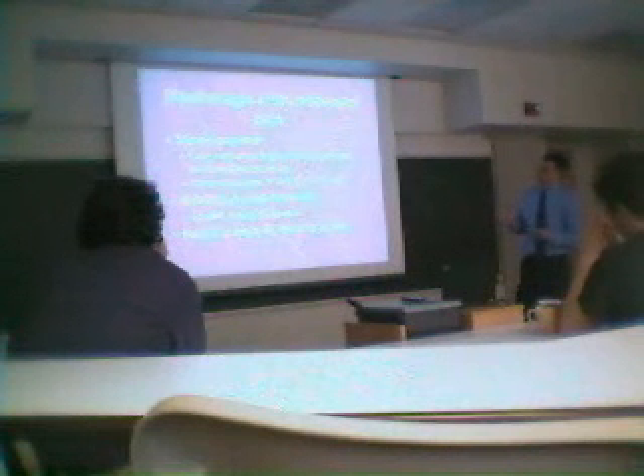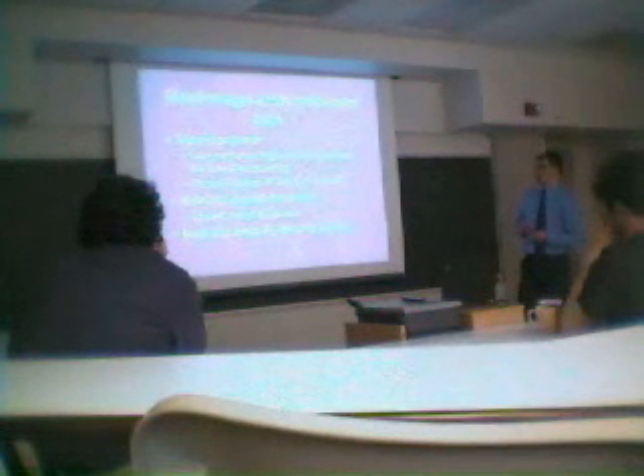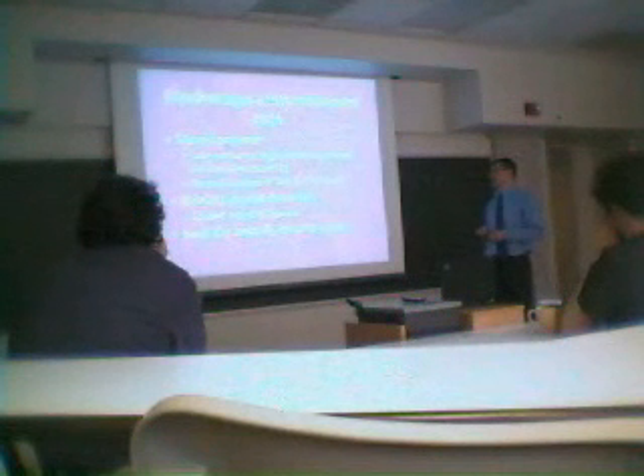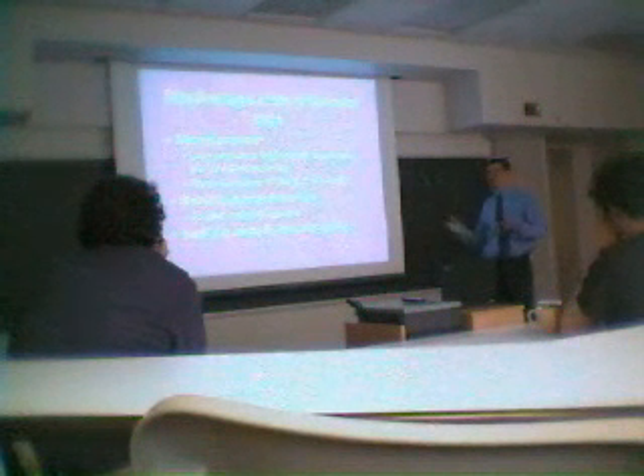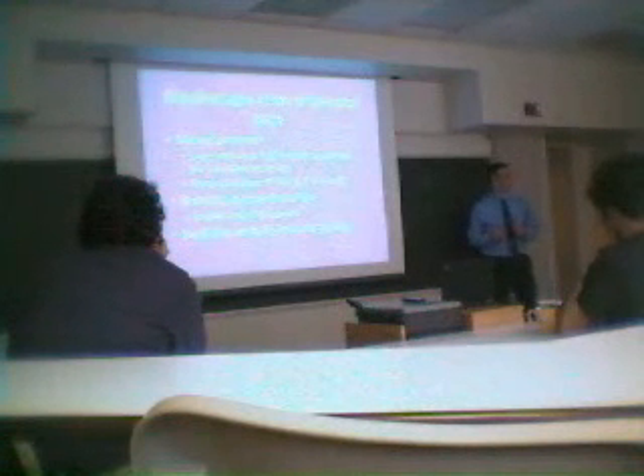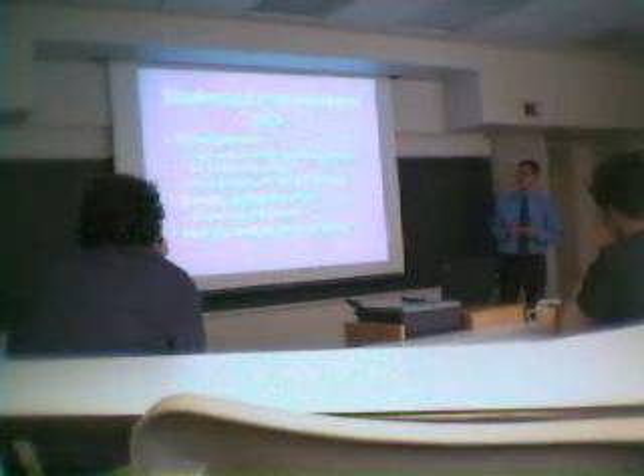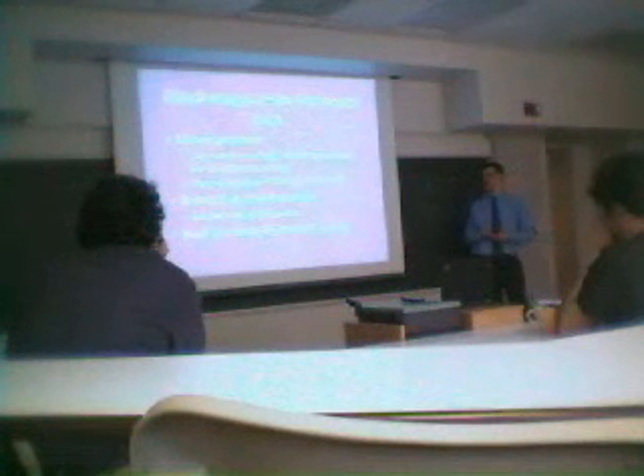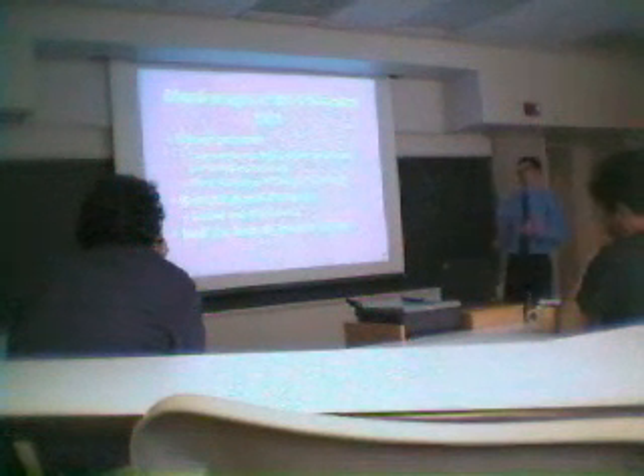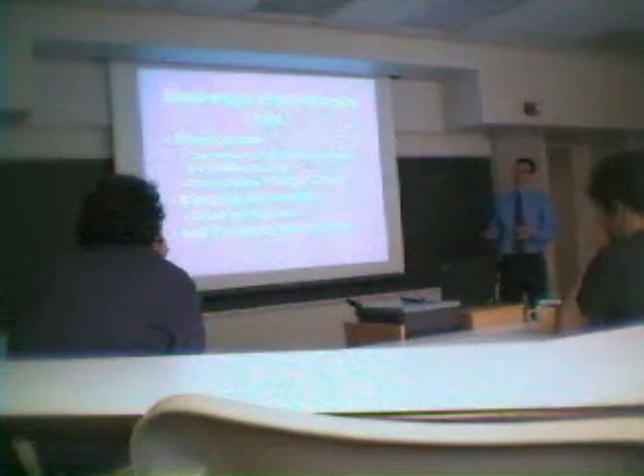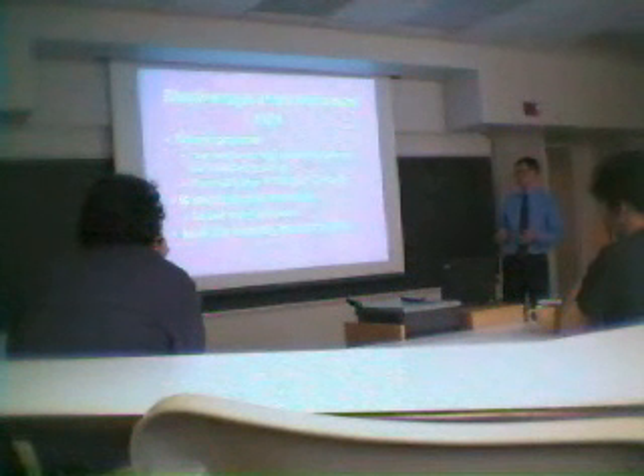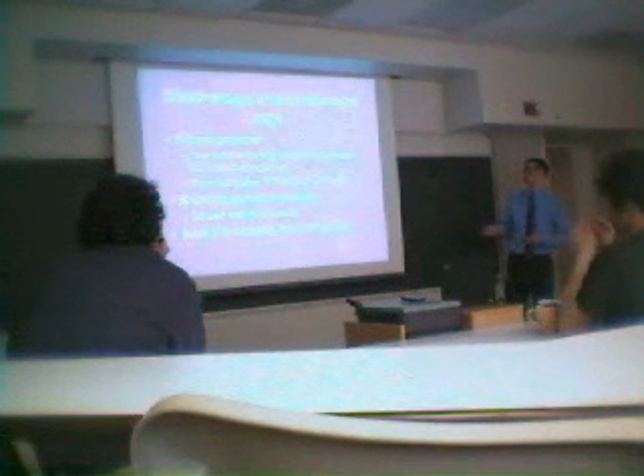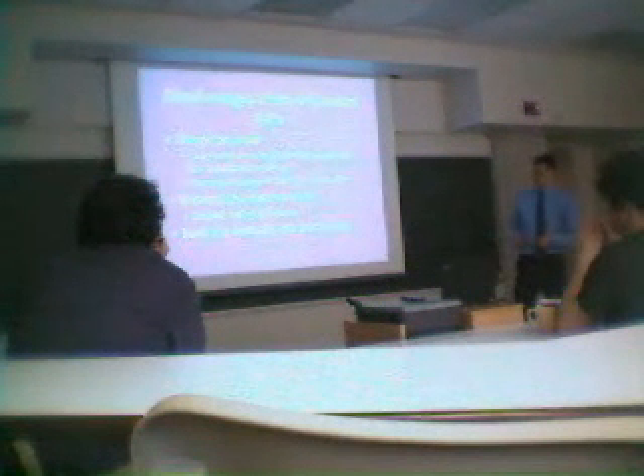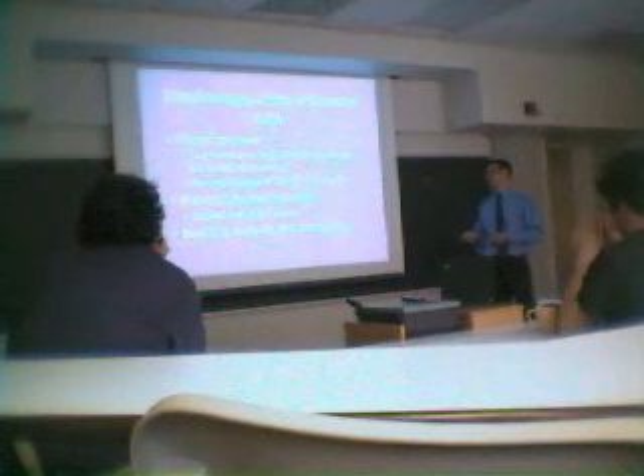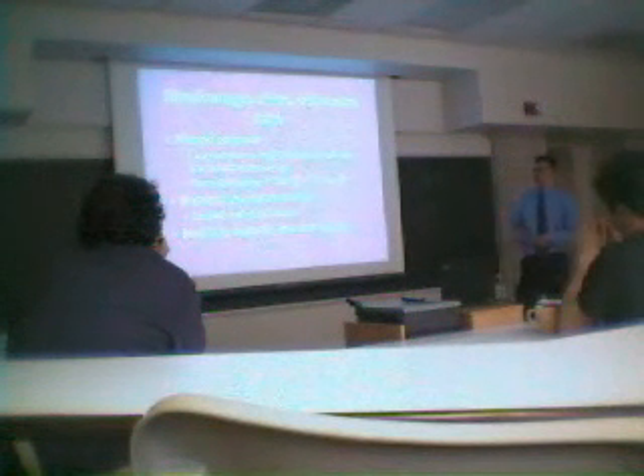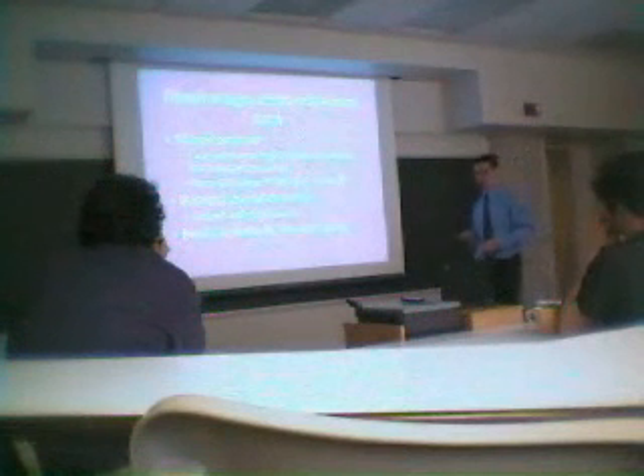Another disadvantage to these traps is that you have restricted physical dimensions. Typically, that is most restrictive in the vertical dimension because if these traps are patterned with MBE growth or with oxide growth, the amount of material you can grow vertically is limited by system requirements. In the lateral dimensions, that is not really a key consideration because you just change your mask, but in the vertical dimension, it is. And finally, the small size of these traps, meaning the distance from the ion to the electrode, has a negative effect on the heating, as I mentioned earlier, the motional heating of the ion.